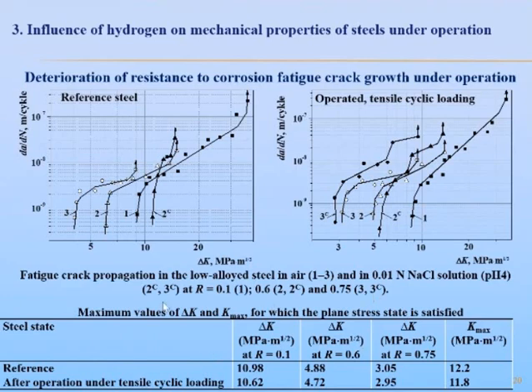So as can be seen from this data, these values of stress intensity factor range, for the minimum thickness of specimens to ensure plane strain state, are in the near threshold region of the fatigue growth curves. Therefore, only the threshold stress intensity factor range can be considered as a characteristic of the steel. And the difference in fatigue growth rate revealed for different stress ratios is associated mainly with a decreasing effect of the fatigue crack closure effect at increasing stress ratio.